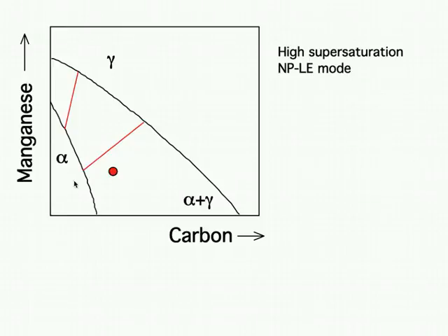In other words, we have a high driving force for transformation. For the manganese concentration in the ferrite to be the same as that in the alloy, we draw a horizontal construction line through the ferrite. Where it intersects this boundary defines the tie line governing the interface compositions, and therefore we get negligible partitioning of manganese and long-range diffusion of carbon.